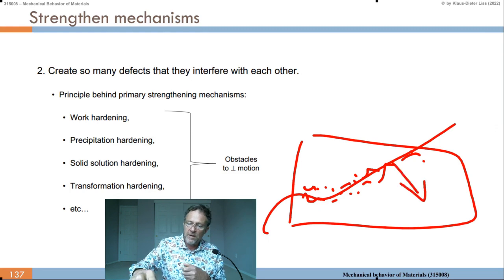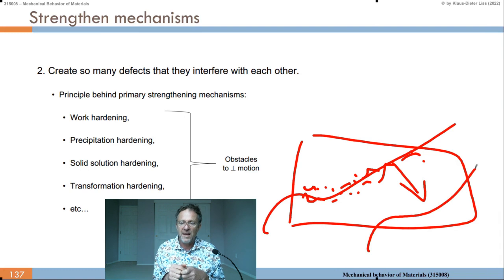So now, if you want to move the dislocation from there to there, you first have to overcome this cloud of solutes, which move by diffusion. So, by mechanical movement of the dislocation, by shear, you need to overcome now this widened lattice, which you may want to compress in the next state as the dislocation moves on. And that's more difficult because there's carbon sitting there. So it's harder to move.